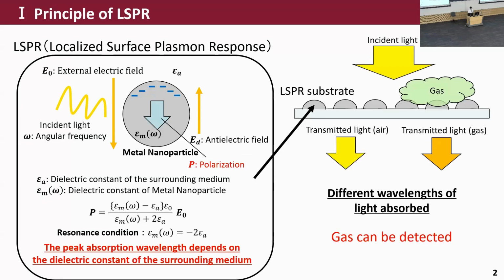I will explain the principle of LSPR. When a metallic nanoparticle is irradiated by incident light, polarization P is induced. The P is expressed by the following equation, and the dielectric constant of the metallic nanoparticle has an imaginary part, so P does not become zero, but takes a very high value. The resonance condition in this case can be expressed in terms of the dielectric constant of the surrounding medium. In other words, the absorption peak wavelength of the metallic nanoparticle depends on the dielectric constant of the surrounding medium.